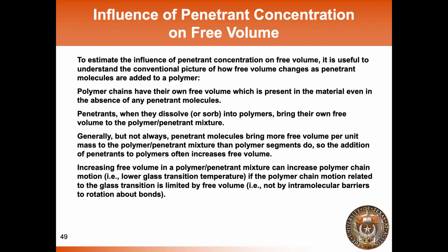Now, this relies on the fact that it's true when polymer chain motion is limited by free volume, that is, by the intermolecular barriers to motion. In other words, I can't move because you're in my way, sort of thing. If I can't move simply because I'm old and stiff, then you won't see this last correlation. So, if there are strong intramolecular contributions to the glass transition, moving the polymer chains further apart won't necessarily increase the rates at which they move.